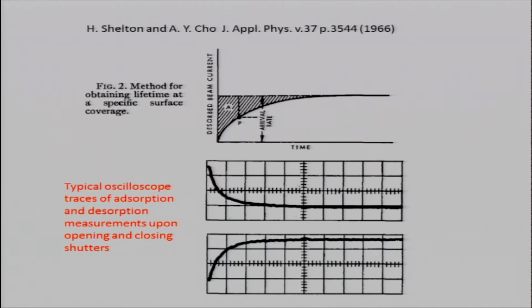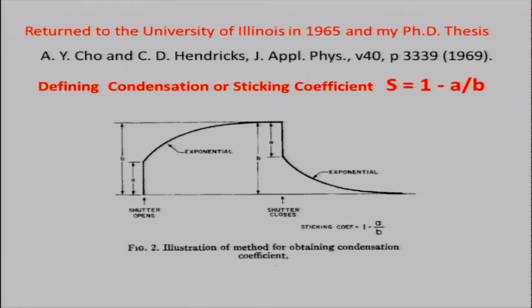I had to study and read in German, a German thesis by Kahn, to try to understand how a quadrupole mass spectrometer works. We built ourselves this quadrupole mass spectrometer with electronics, and then we did the measurement. And of course, 5 years later, like 1967, this became commercially available. As John Arthur alluded to earlier, when you open and close the shutter, you see the exponential curve on and off. And then by looking at the lifetime of that, you plot the Arrhenius plot. You get the activation energy of these molecules on the surface.